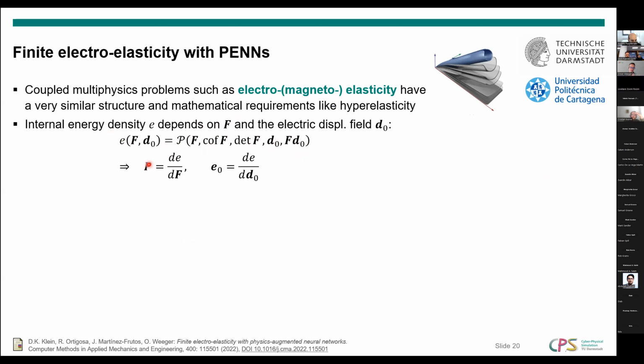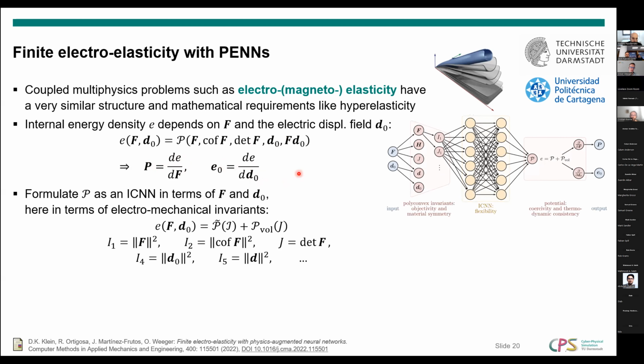And then we can get the stress as the derivative of this internal energy function with respect to F, like we had it before, and we can get the electric field as the derivative of this function with respect to the electric displacement field. So the idea now is to, again, just use an input convex neural network in order to represent this internal energy, where now we use invariants as inputs, which makes life a bit simpler because we only have like 5 or a few more invariants depending on the symmetry group.